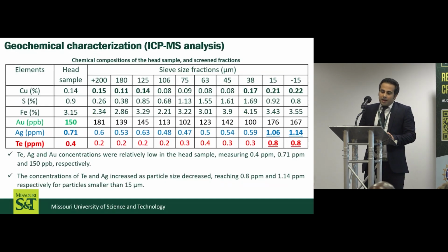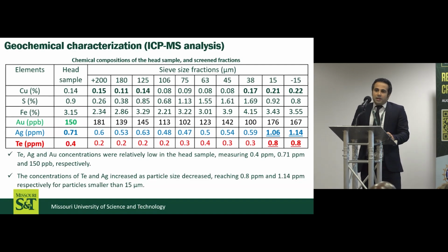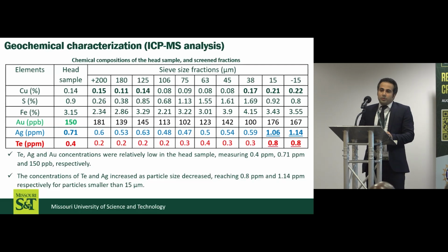ICP-MS analysis showed that the head sample contained 0.14% copper and 3% iron. Tellurium, silver, and gold concentrations were relatively low in the head sample, measuring 0.4 ppm, 0.7 ppm, and 150 ppb, respectively.